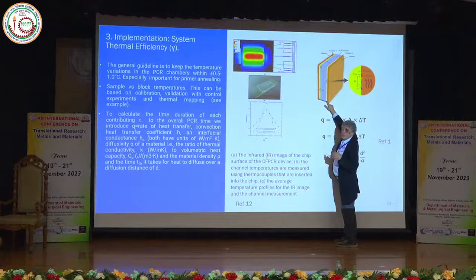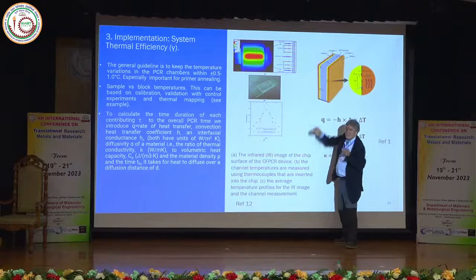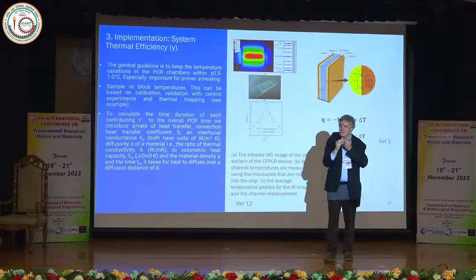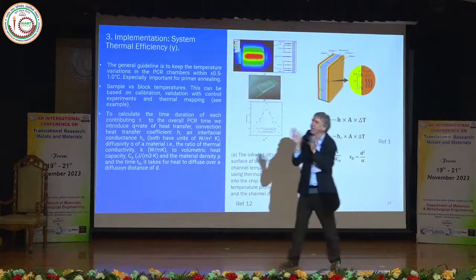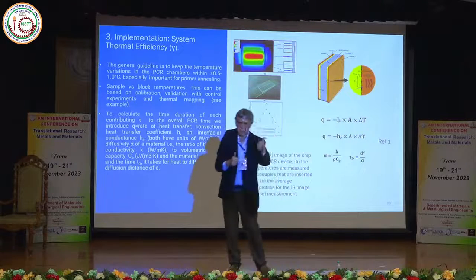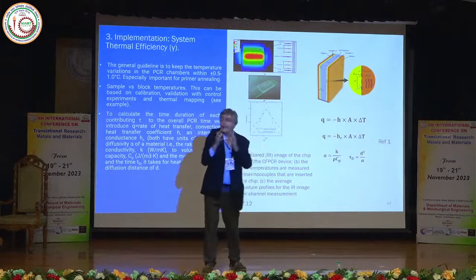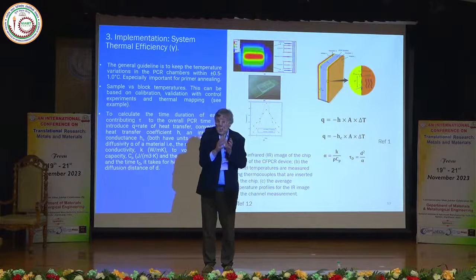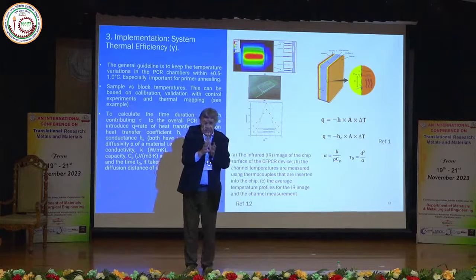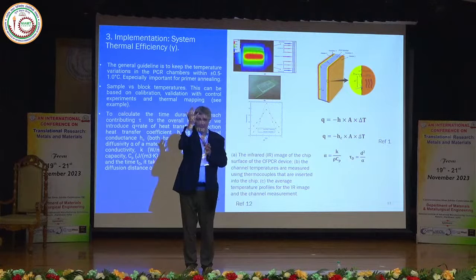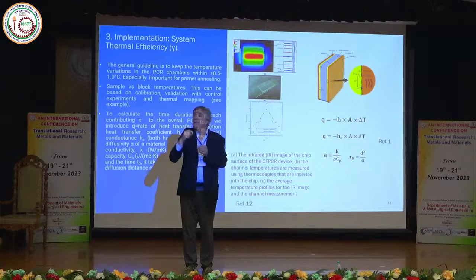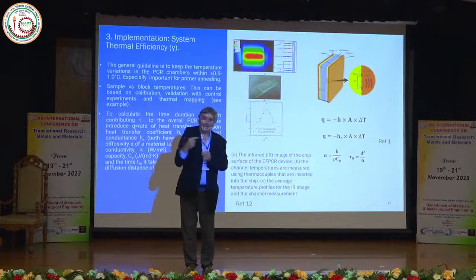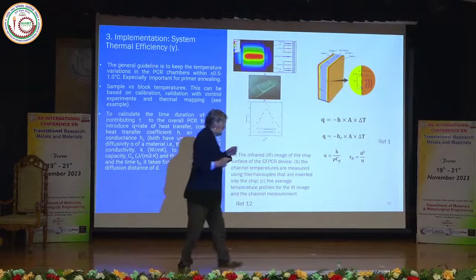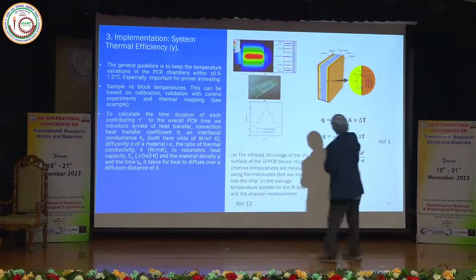We ended up having to specify and make polymer composites that had the right heat diffusion coefficient, because you can imagine what would you want from that polymer. It needs to be transparent. The heat capacity needs to be small because, you know, if it has big heat capacity, it will take a long time to heat it up. And the heat diffusivity should be very fast, right?